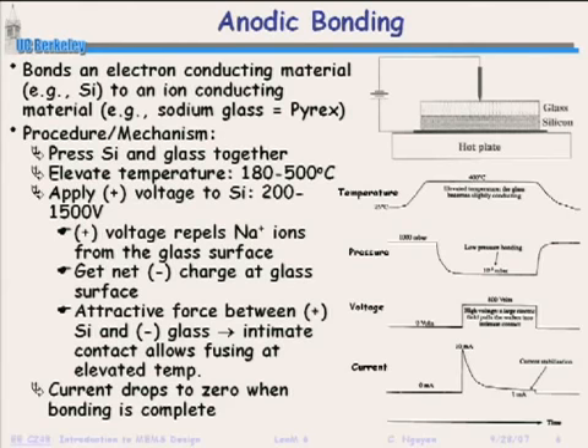So an electron-conducting material, obviously silicon is one of them. But an ion-conducting material is something like sodium glass, which is the same as Pyrex. Right? So that's glass that's impregnated with a lot of sodium ions in it. And so the mechanism for doing this is sort of shown to the right here. What you do is you take the silicon and the glass and you press them together. You still need to get this up to temperature, but it doesn't have to be a very high temperature. It could be temperatures between 180 and 500 degrees C.